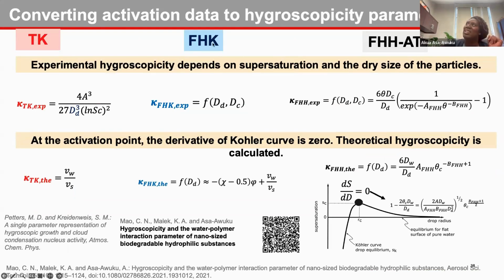So let me give this a quick summary. That is, we have 3 different types of models that we can apply. That is traditional Köhler theory, which assumes everything dissolves. We have total insoluble theory, which is FHH, adsorption theory, which assumes that the core stays intact. And we have FHK, which is Flory-Huggins Köhler theory, which assumes that the aerosol behaves as a polymer that can swell in the presence of water.